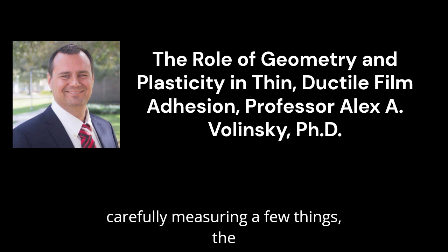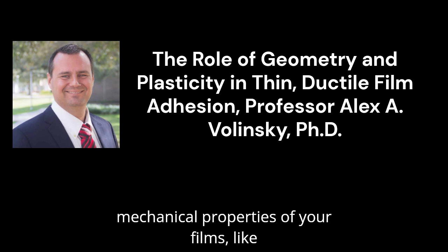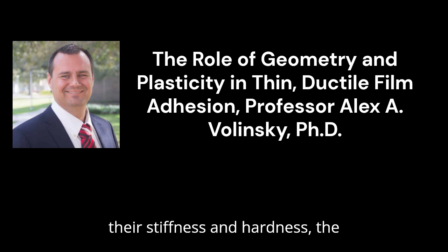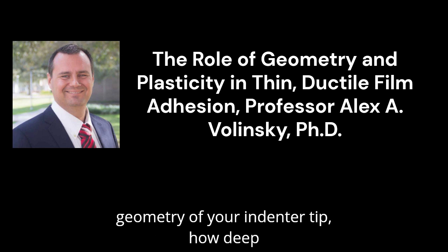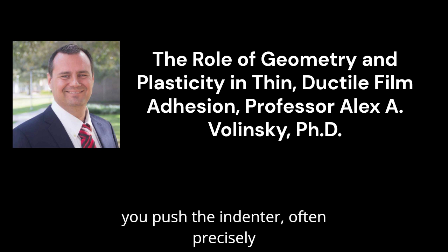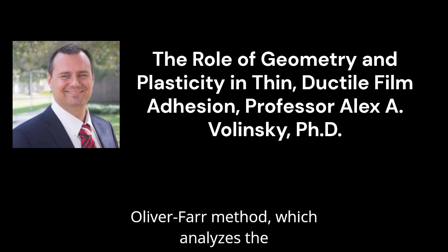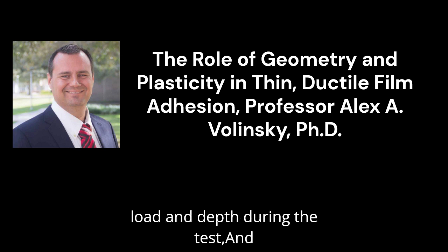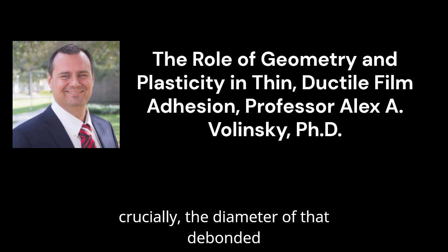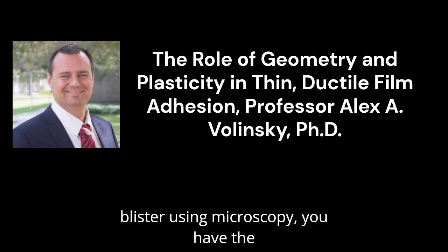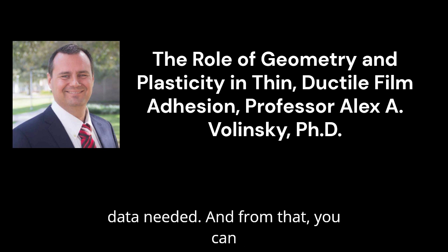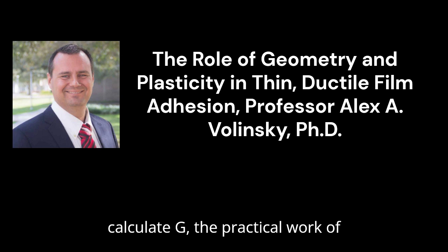Exactly. And by carefully measuring a few things: the mechanical properties of your films, like their stiffness and hardness, the geometry of your indenter tip, how deep you pushed the indenter, often precisely measured using techniques like the Oliver-Pharr method, which analyzes the load and depth during the test, and crucially, the diameter of that debonded blister using microscopy, you have the data needed. And from that, you can calculate G, the practical work of adhesion.